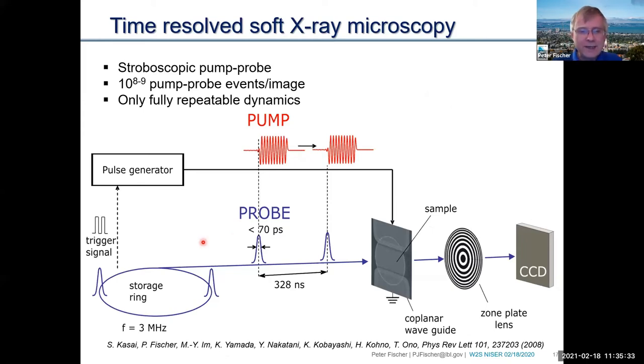And the way it works is the electrons inside the storage ring that generate these X-ray pulses are coming in little bunches. So when you use a trigger signal from the storage ring to feed a pulse generator, generate, let's say, a pumping pulse, and you feed this through a waveguide into a spin texture, you will excite it, and it could be either a field-driven or a spin-torque-driven excitation of the dynamics. And then you basically take snapshots at a specific delay time between the pump and the probe, and you generate image after image. Because you have a high spatial and temporal resolution, that's about 100 picosecond, or probably a little less than that.